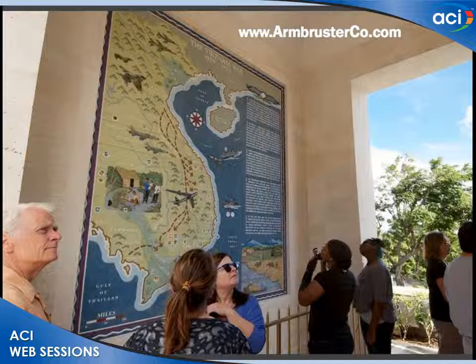But we felt not only with the pozzolans, but with this dense packing of the aggregate that we had done our best. We also had the 50-year-old maps, murals to go by, the mosaic murals, and they didn't use any pozzolans. They used straight Portland, and there was no damage. The Hawaii climate is very consistent. Freeze-thaw wasn't an issue. We didn't have to worry about air entrainment. They're in a gallery that's covered, except for one open side. I think it's rare if they even get rain. So the existing maps are in superb condition.